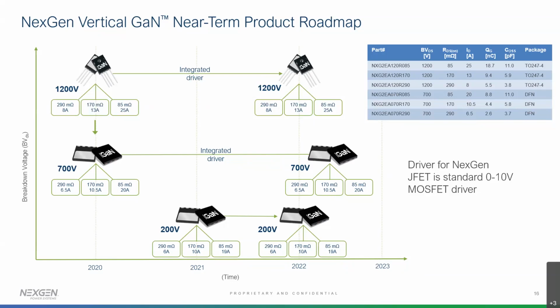Okay, what is the thickness of the vertical GaN? So let me give you two answers to that. Wafer thickness, if you're looking at that, is about 450 microns. And then thickness of the material depends on what type of breakdown voltage you're trying to achieve. There are a bunch of papers out there that you can read, but I'll give you a rule of thumb. Rule of thumb is about a micron per 100 volts.